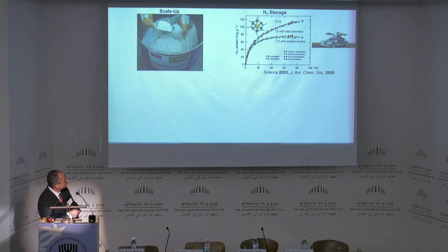At room temperature, this material takes up about 2 weight percent. And that's interesting enough for Mercedes to build a demonstration sedan, a hydrogen car with a fuel tank that has a MOF pressurized with hydrogen.